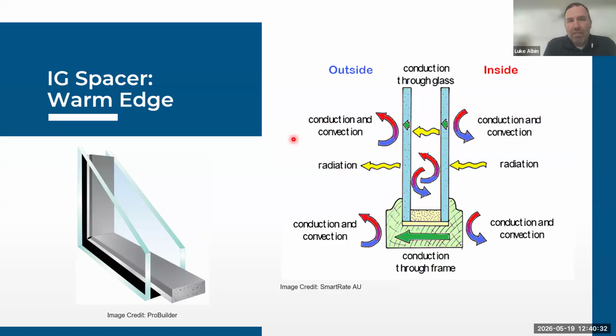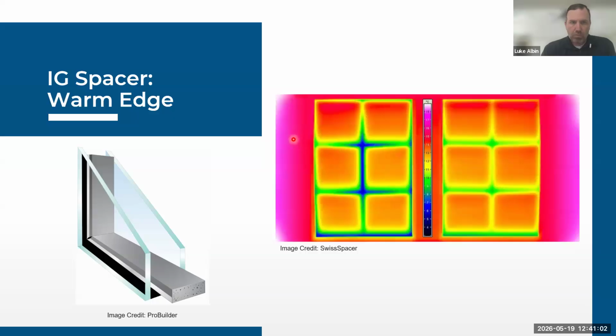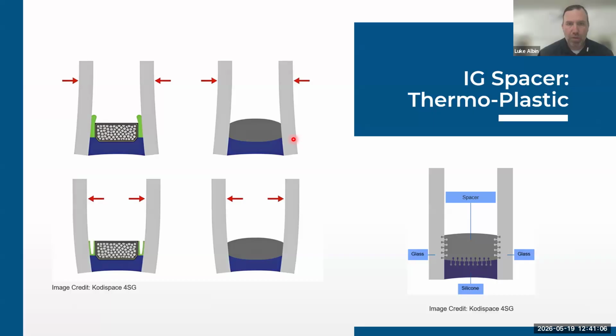So we now have, and have had for quite some years now, warm edge spacer. Primarily, it's a dense foam product, and as you can imagine, that foam product has much less heat transfer than your stainless steel spacer does. That's typically used within the high performance window range. But there's more. A subset of the warm edge spacer is the thermoplastic warm edge spacer. The best way I can describe it is it's almost like a hot melt glue that cures. It bonds itself not only to the silicone bed, but also to the glass as well.